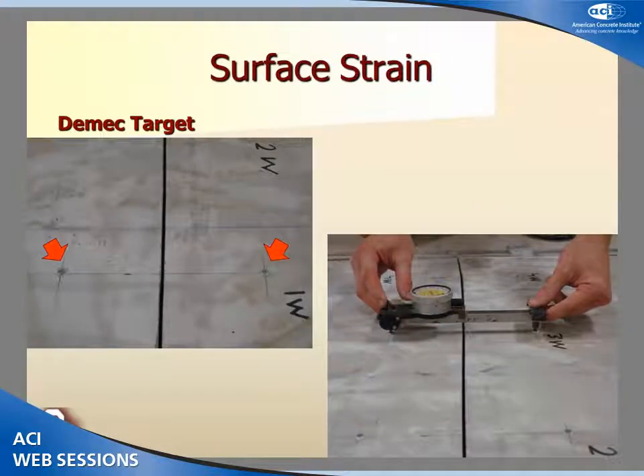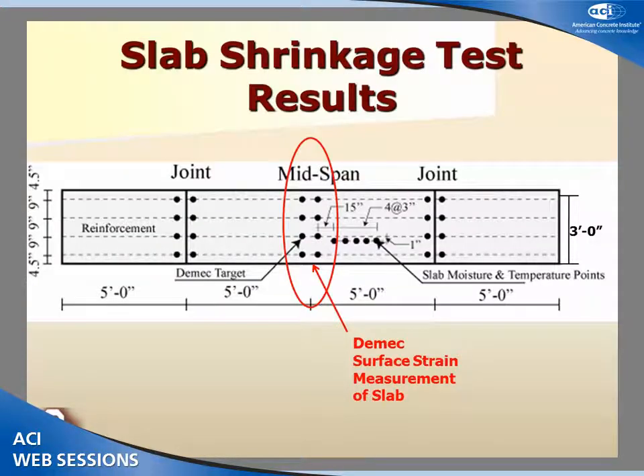As I mentioned before, we attached some DEMEC targets at the joint opening and mid-span to measure the surface strain of the concrete slabs on ground, and here is the gauge we used to measure this. Now I'm going to review some data we measured at the mid-span of the slabs.